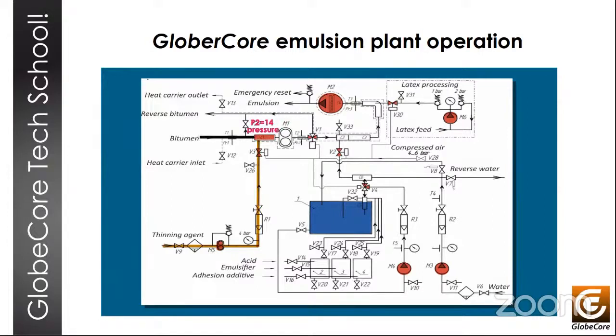After switching the bitumen valve V1, the bitumen enters the mixer nozzle at a pressure of 14 bar. In the C1 mixer, the thinner and bitumen are premixed. The flow rate of the thinner is controlled by a flow meter R1, and it's adjusted with a control valve.